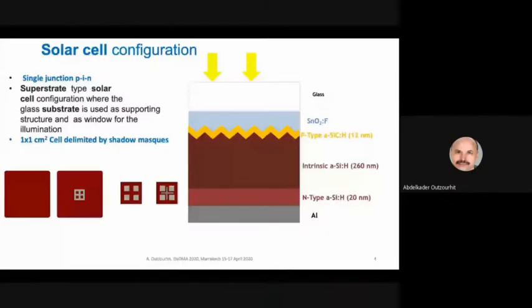This P-type film acts both as a window layer and also as a carrier selective layer, because it only allows holes to pass through. This layer is followed by an intrinsic hydrogenated amorphous silicon film of about 260 nanometers thickness, which is the active layer where the photogeneration of carriers takes place. This is followed by an N-type layer consisting of hydrogenated amorphous silicon N-type layer of about 20 nanometers, which is also in this case a carrier selective layer, which only allows the passage of electrons.